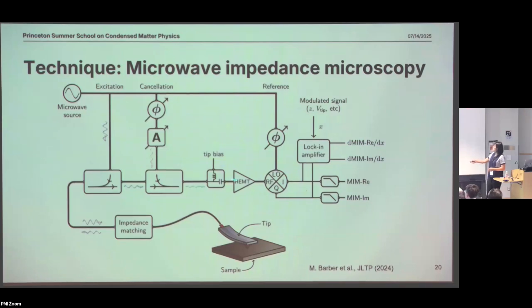And then it goes through a cold amplifier at 4 Kelvin to amplify the signal, and it goes to this IQ mixer. So this mixer just down converts the microwave field to DC, because at DC, we can have different lock-in type of measurements where we can get both the DC part of MIM and also the AC part. If we modulate the tip by its height, we modulate the bias applied to the tip or gate on the sample, etc., then we can also get the dMIM over dZ or this quantity.